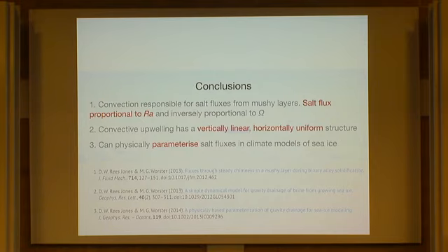That kind of ice is collimated, and microstructural models suggest it could be something like a factor of 10 more permeable in the vertical direction than in the horizontal direction. The only previous modelling study I saw was a factor of 2, but it doesn't really change the overall story. Yes, you're right that sea ice is very anisotropic in its permeability.